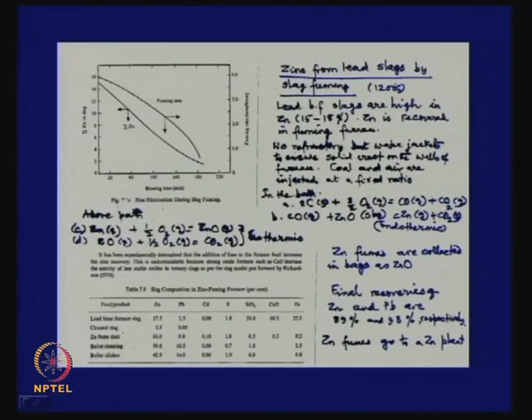In that furnace, in the bath, you have to go to this temperature because you are treating slags, and melting points of slags are around that, a little below. To that is added coal, injected coal and air. So, you are actually gasifying coal inside a slag phase. So, coal will form CO and CO2 on gasification. This CO reacts with ZnO in slag to form zinc vapors.